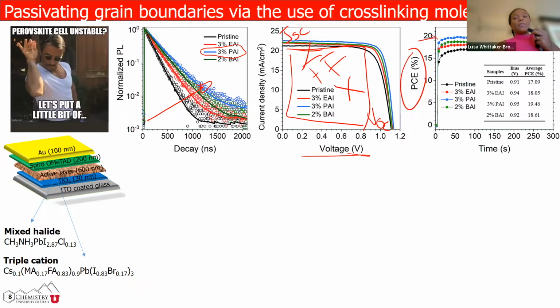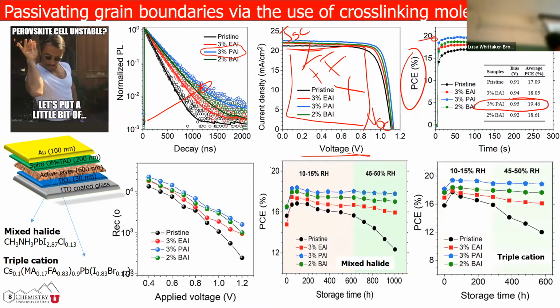So again, we are around 20% versus 25% for the highest. And then for the propyl ammonium, we are at 19.46. I already told you that these materials degrade very quickly, so we actually have to look at the recombination. We know that there is a decrease in recombination when we use propyl ammonium iodide. And now stability in air and humidity conditions. So we actually did look at the power conversion efficiency as a function of storage time in air, under light conditions. So this is under illumination.